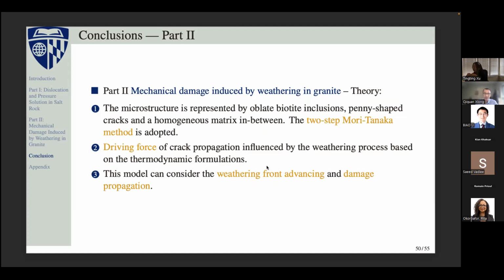And in terms of the theoretical part, first of all, at the material point scale, we use the two-step Mori-Tanaka method to consider both the microcrack propagation and also the biotite expansion. And on top of that, we're using a thermodynamics-based model to consider how the microcrack propagates based on the driving force. And by combining the bulk element and the cohesive zone element, we can simulate the feedback mechanisms between the weathering front advancing and the damage propagation. So that will conclude the talk today.